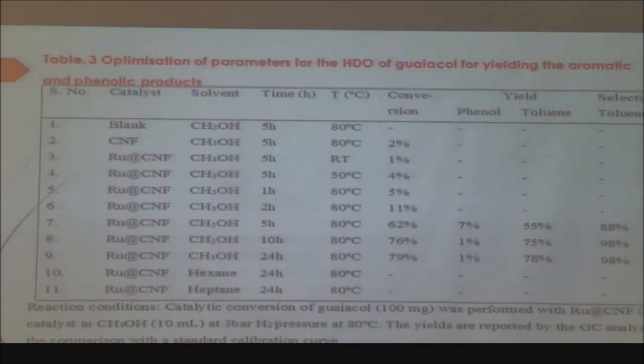So now coming to the test in the laboratory, we again performed reactions. This is the one that I have done in India; the previous one I did in China. I performed this in India at Shoolini University. Here we again did a lot of reactions, multiple reactions. And we were able to get conversion in 24 hours, that too at 80 degrees centigrade. We don't have the facility to take the temperature to a higher range, so otherwise conversion could have been better. The maximum temperature we could attain was 80 degrees centigrade, and we performed that for a maximum of 24 hours. We even tried 40 hours, but there was not much difference. Maybe the catalyst was saturated by that time.